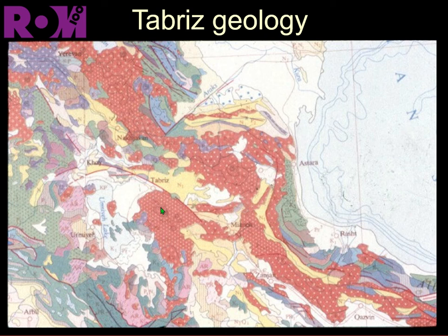Practically unique situation, and so that led me to hypothesize that this pottery came from Tabriz. As a result of this hypothesis, I acquired kiln evidence and tiles and other things that don't travel around so much from Tabriz, and was able to characterize this fabric as coming from Tabriz based on finding so much volcanic rock in it that there was no quartz.